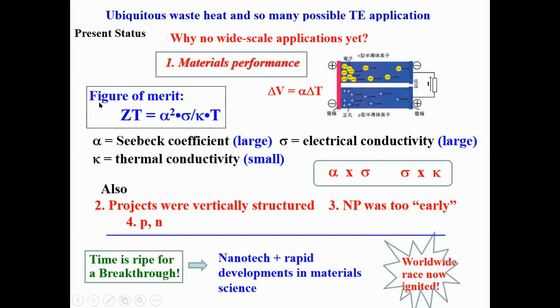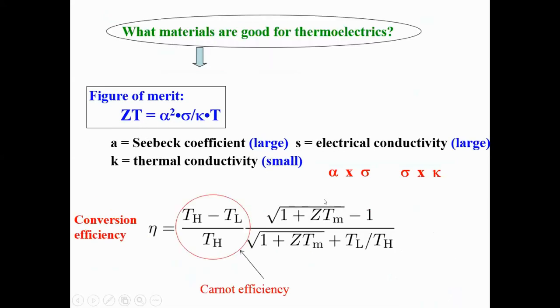So fortunately for us, we have a very good way to measure the performance of thermoelectric materials called the figure of merit, and it's based on very fundamental, simple physical properties. So no complex application, but just really fundamental science. You can get this ZT. One benchmark is that more than one is usually considered to be a good performance thermoelectric material. And the ZT is related to the conversion efficiency. So this is the ideal efficiency. If you have ZT of infinity or very large, it will approach this Carnot limit, the ideal efficiency. So of course, we want to get the ZT as large as possible.